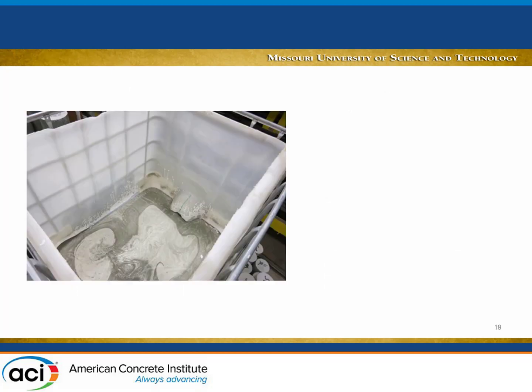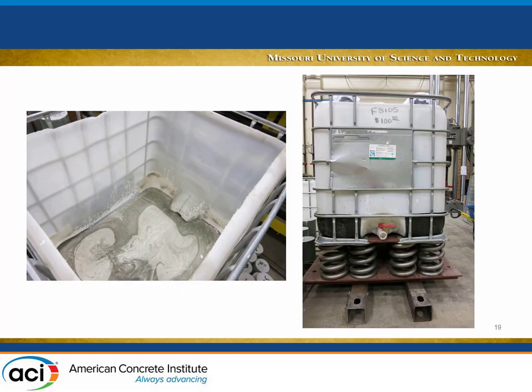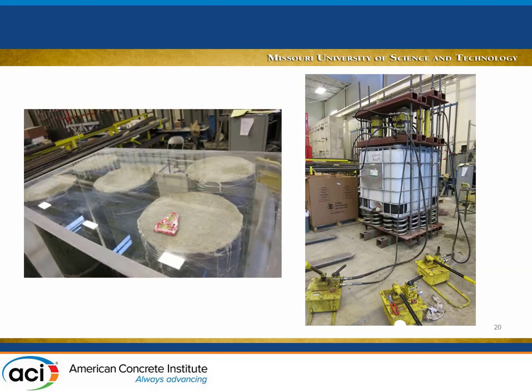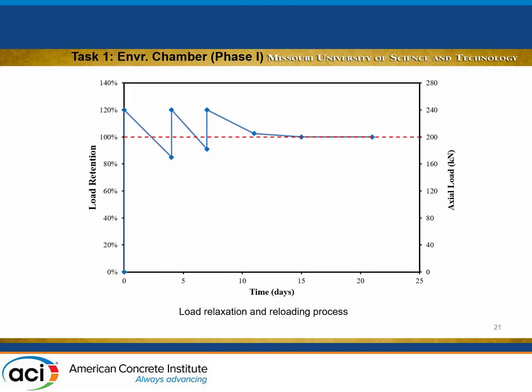And this is a tank. This is how the test setup looks, and this is while we are loading the test specimens. So this is the very first few days. In the first 15 days you have some variation in the unbonded post tension. You load, you lose some load, you go back and load, and so on until, after about 10 to 15 days, you start to see a constant load on the specimens.